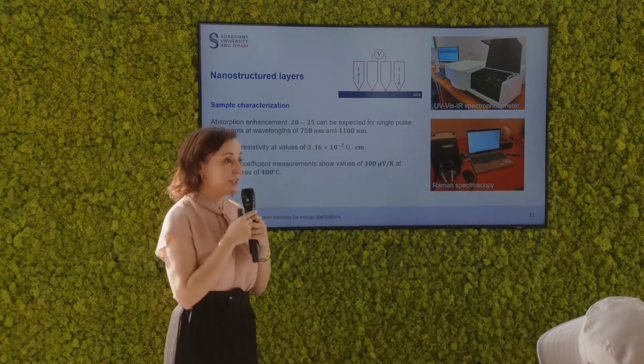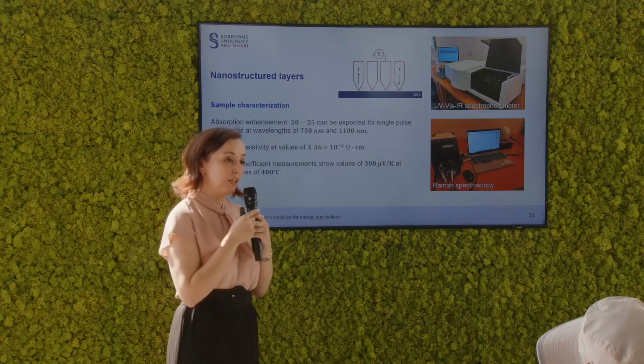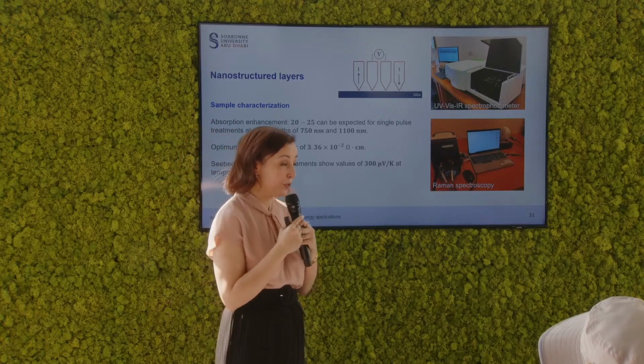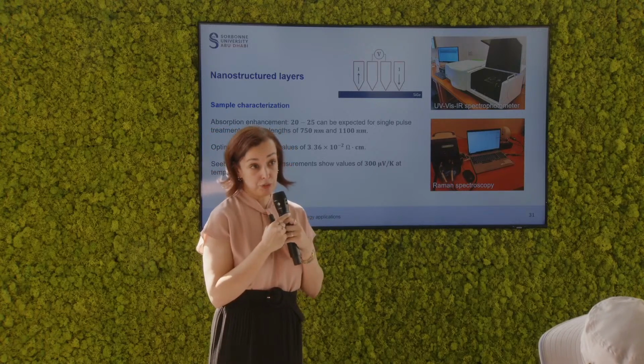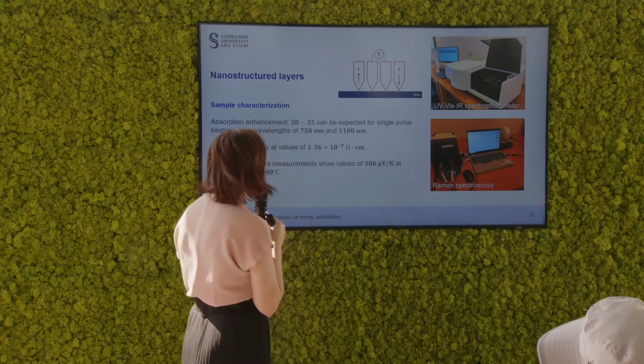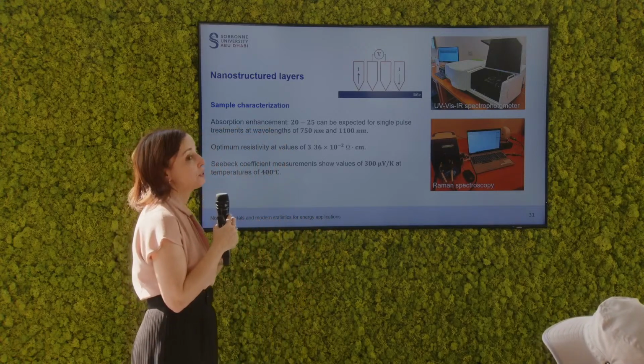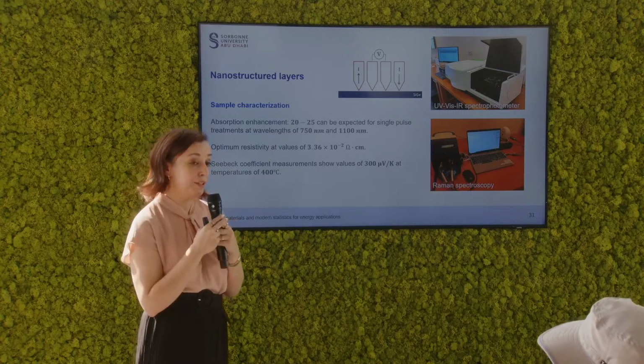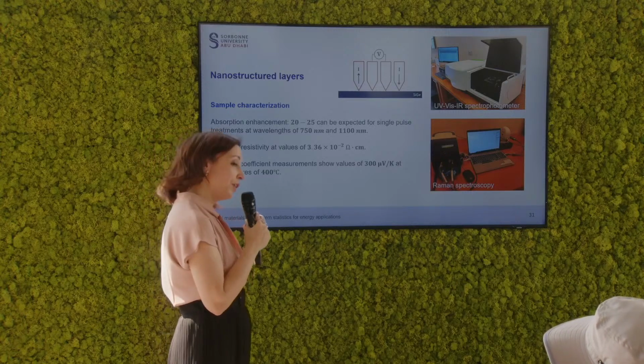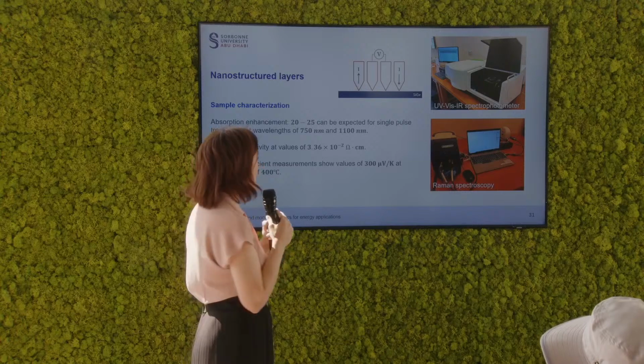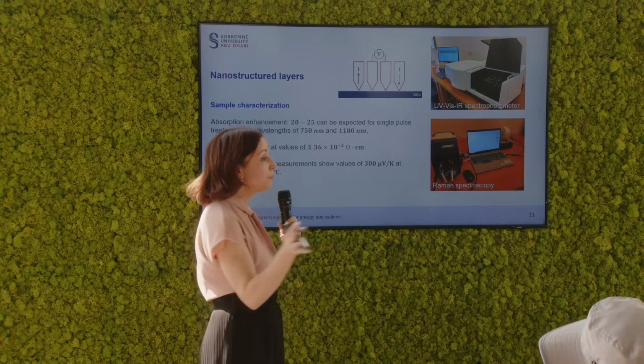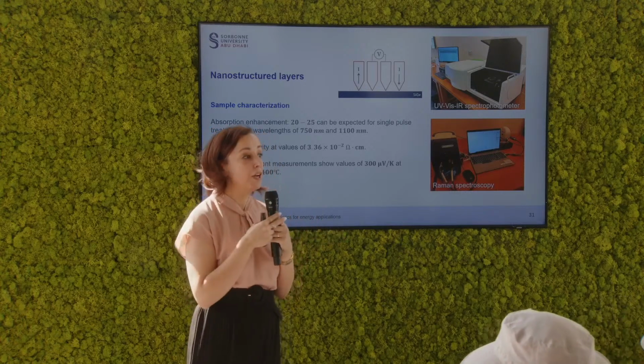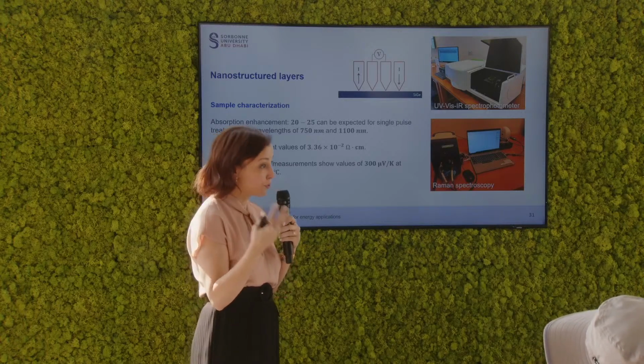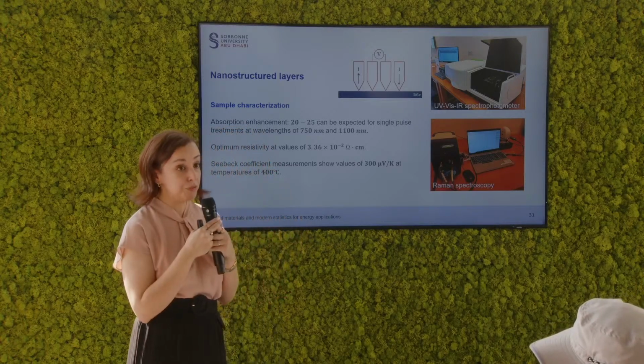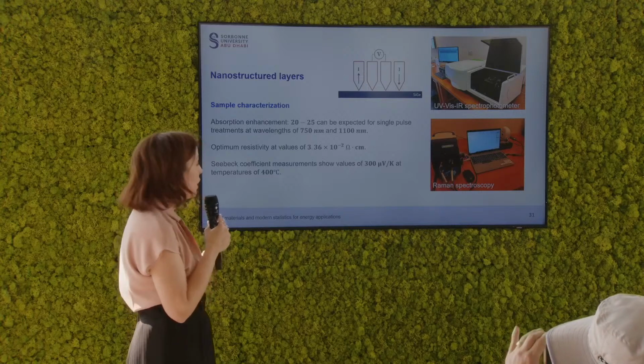We have measured the samples using a UV visible infrared spectrophotometer to analyze its absorption of light over a large scale of wavelengths. And we see an absorption enhancement of a factor of 20 to 25 at 750 nanometers and 1,100 nanometers. So it has improved, and it can be tracked to the laser pulse itself or to laser treatment, can improve the absorption of your initial layer.